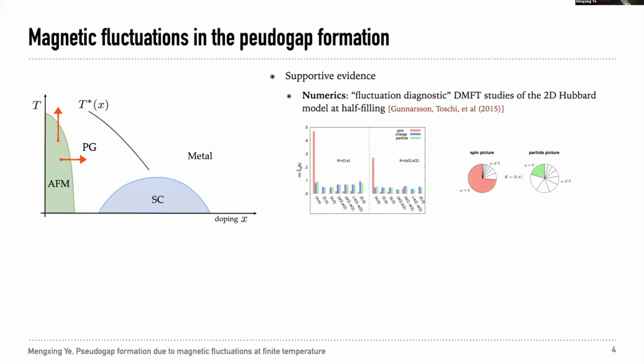And there has indeed been supportive evidence for fluctuations in the pseudogap formation. One important piece of evidence is from numerical studies using DMFT, where from this left panel plot, you can see that the spin fluctuation is the dominant fluctuation channel. To be specific, it is an antiferromagnetic fluctuation. And from this right panel, you can see that the static fluctuation dominates. So for this reason, I will consider the effect of the static antiferromagnetic fluctuations.